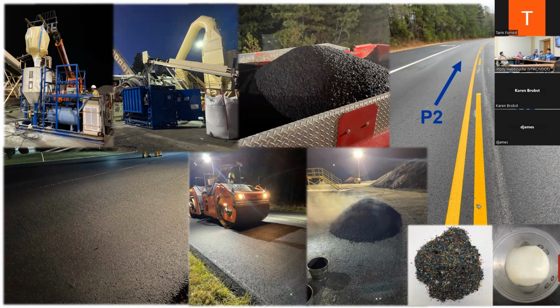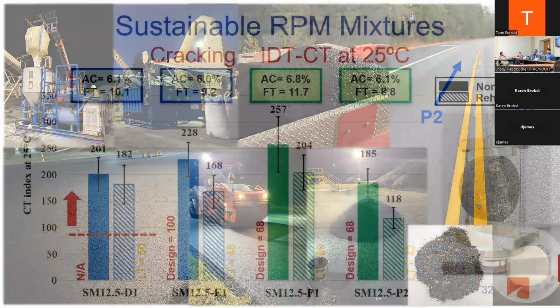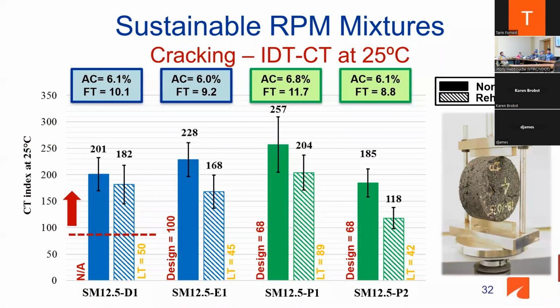No changes in paving operation. Standard practice was followed. The paving crew was not subjected to any harmful fumes and so on. And again, at the bottom right, these are the plastics that were used in that trial. Again, I want to look at cracking. If we're going to go with maybe the solid, the blue one, we noticed that the plastic mix shows similar or better cracking performance compared to our control. That means that the engineering framework that we adopted to design and produce these mixes was useful and helpful and put us on the right track.